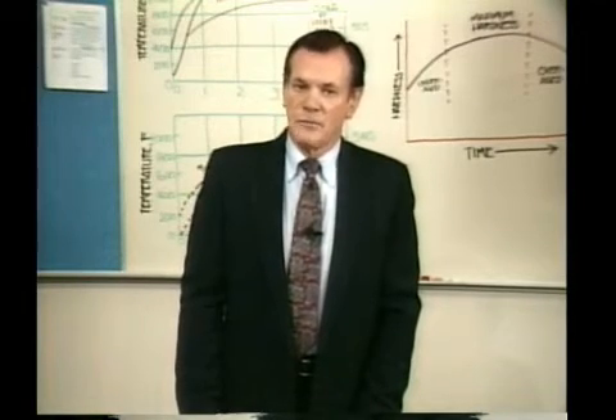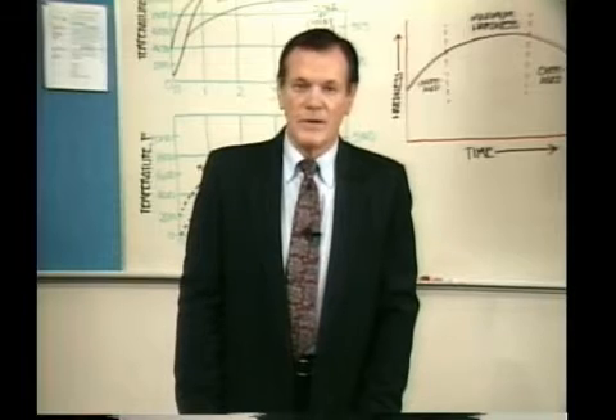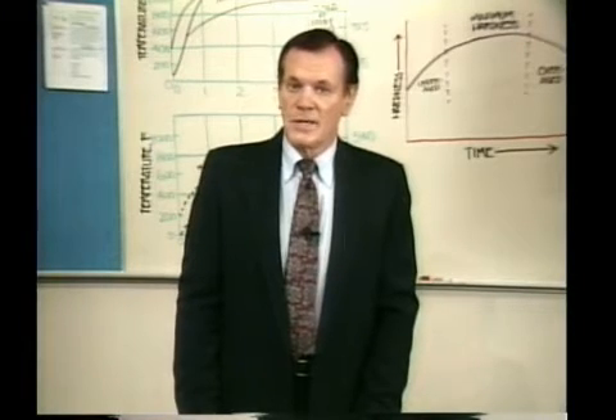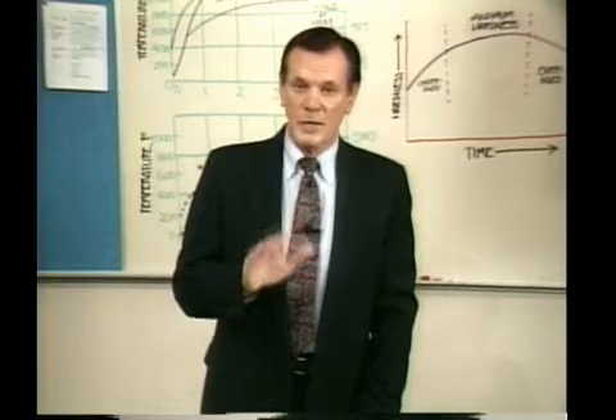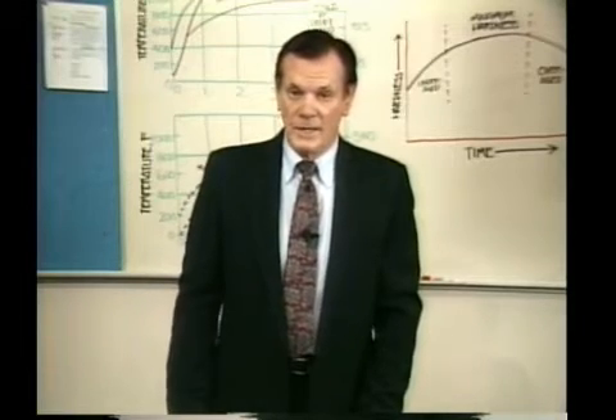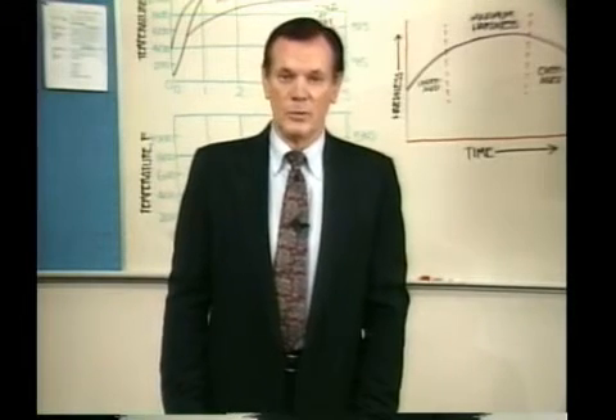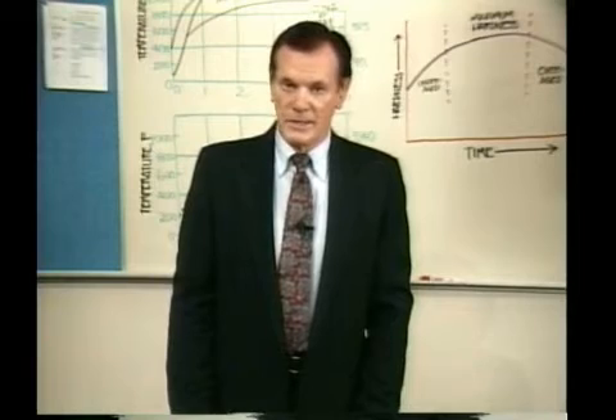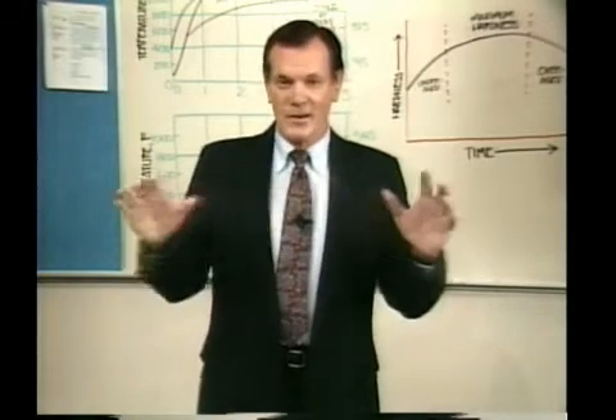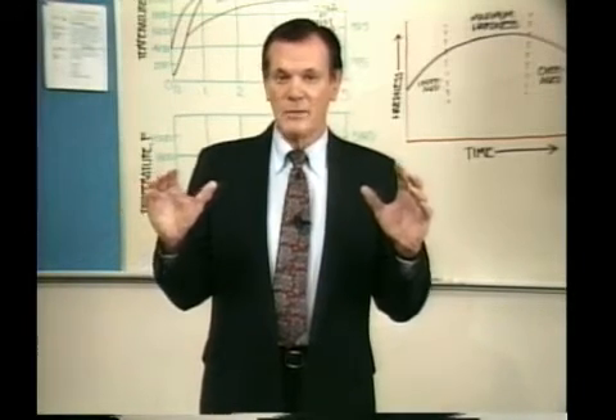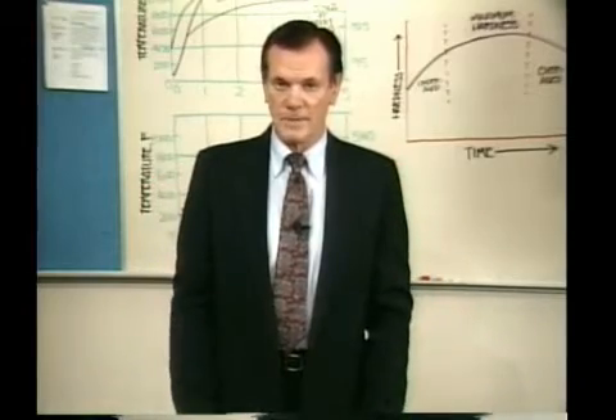The eutectic that forms in the grain boundaries can severely damage the material such that the parts will show no measurable ductility. In one instance, a cast aluminum automobile wheel, which had exceeded the eutectic temperature, actually shattered into about 20 pieces when it was accidentally dropped after quenching.